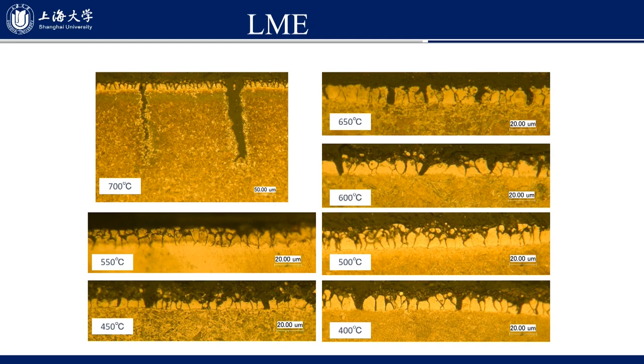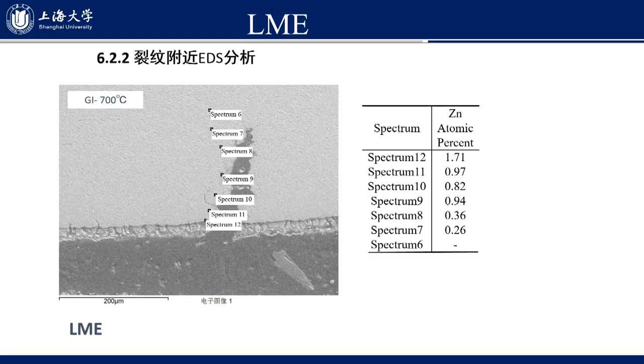The reason for the microcracks is liquid metal embrittlement. During thermal deformation, the working temperature is high. The zinc-rich liquid surface layer penetrates along the austenite grain boundary and finally leads to embrittlement.